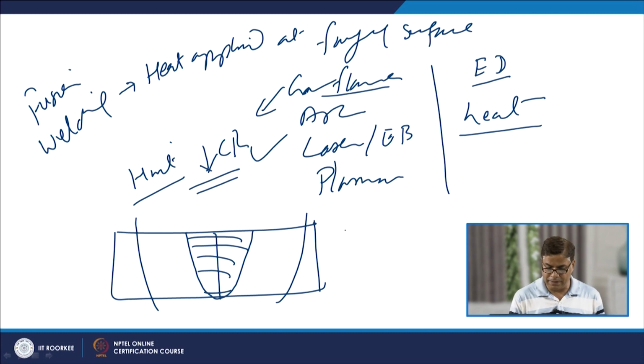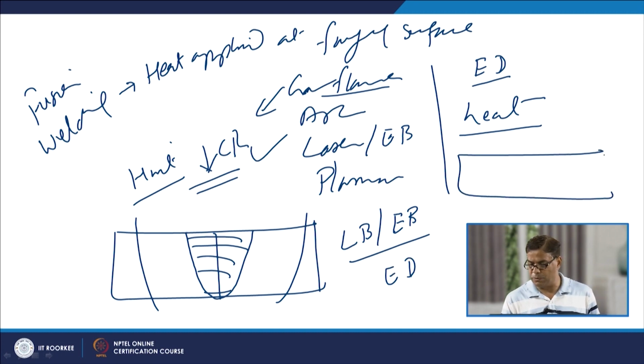On the other hand, the laser beam and electron beam welding processes offer very high energy density. So, very little heat is required to bring the faying surfaces to the molten state, and a very limited heat affected zone is formed due to the less heat supply. And we know that the cooling rate and the heat input are inversely related. So, the lower heat input leads to the higher cooling rate.